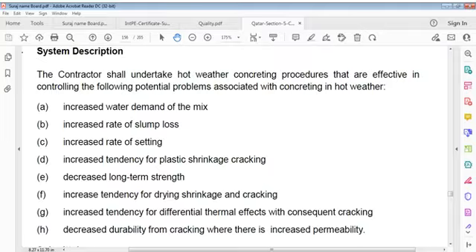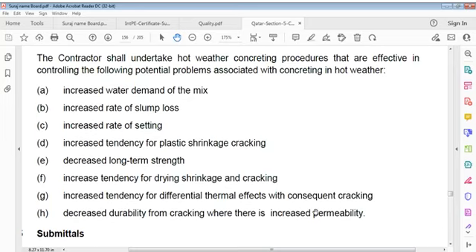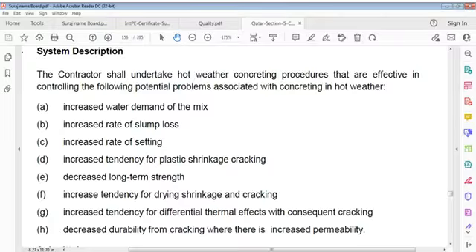Increased water demand of mix. Increased rate of slump loss. Increased rate of setting. Increased tendency of plastic shrinkage cracking. Decreased long-term strength. Increased tendency of drying shrinkage and cracking. Increased tendency for differential thermal stresses, thermal effects with consequent cracking. Decreased durability from cracking where there is increased permeability. So these are very important points.